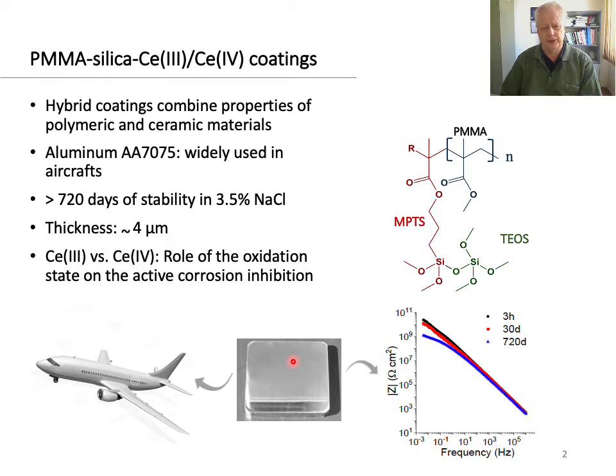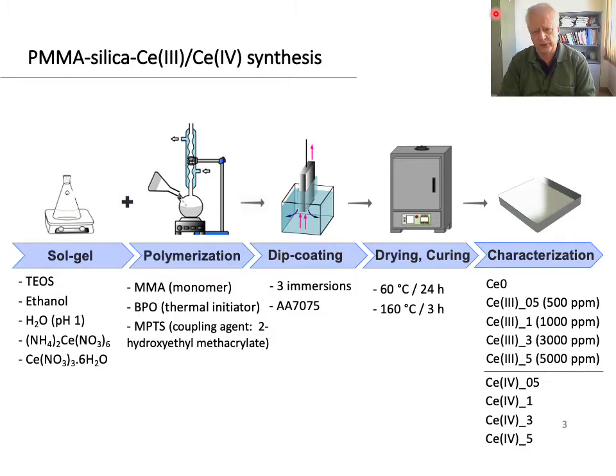For this active protection, cerium salts show very promising results. In this work, we present new insights on the self-healing mechanism of especially cerium-4 in the corrosion and mechanical induced effects. For this purpose, different concentrations of cerium-3 and cerium-4 salts were added separately to the inorganic solution containing tetraethoxysilane in an acidified ethanol water solution, which was then mixed with the organic solution of methyl methacrylate and MPTS coupling agents containing a siloxane group attached to a methacrylate tail, thus providing covalent bonding between both phases.